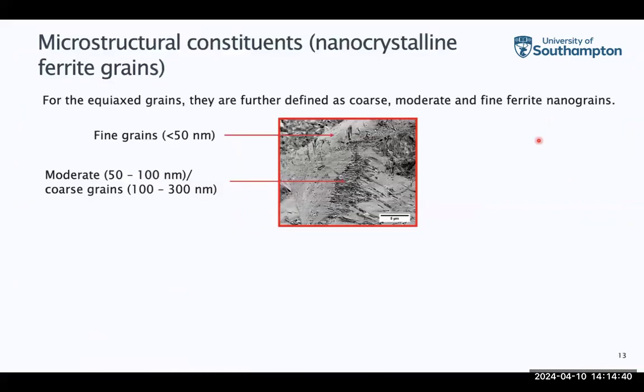With the equiaxed grains, we also separate them into different sizes, and we call them fine grains. They typically appear as very fine structures. For these, we define them as below 50 nanometers in diameter. We also have slightly darker appearing grains, the equiaxed grains, which we call moderate, between 50 and 100 nanometers in size, and coarse grains between 100 and 300 nanometers in size.